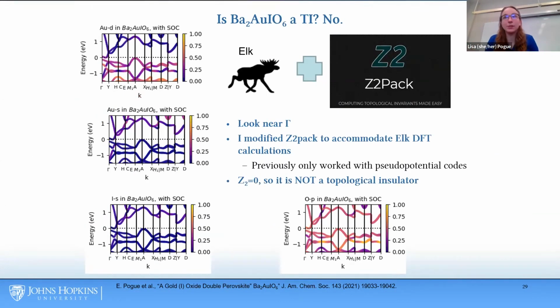To answer the final question of whether this is a topological insulator, I had to modify Z2Pack, which is a Python-based piece of code for evaluating topological invariants, to work with ELK, which is an all-electron DFT code, which I needed because of the very high oxidation state of iodine in the structure. When I did this, I found that the Z2 was 0, so it's not a topological insulator. However, this is still useful because other people can use this process for interfacing ELK with Z2Pack.